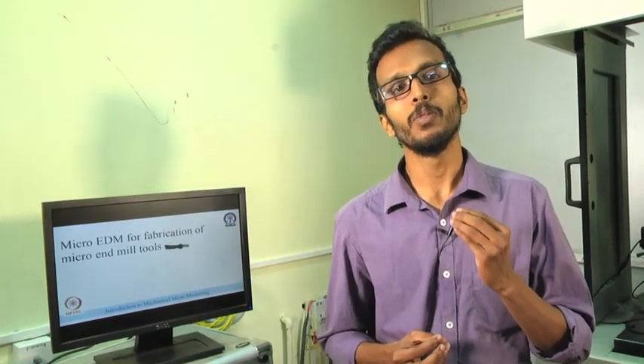So what is a popular tool fabrication process in the macro region? Actually, it's called tool grinding. The tool grinding process is not very reliable in the case of micro machining of cutting tools. Why is that? The tool grinding process is a contact type process, so there will always be cutting contact between the tool and the workpiece. While dealing with very small cutting tools in micro dimensions, if there is high cutting force or contact force on the cutting tool or the workpiece, there will be a chance of breakage. So it's not easy to make cutting tools using grinding.